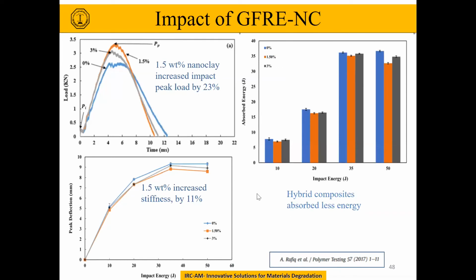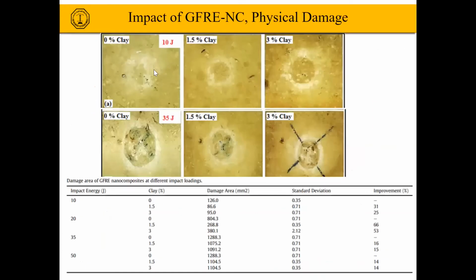We looked also at the impact behavior, and these are some of the results. Again, here, the exfoliated structure has a higher peak load, less peak deflection, and absorbs less energy under impact. Physically, this is what we have observed.